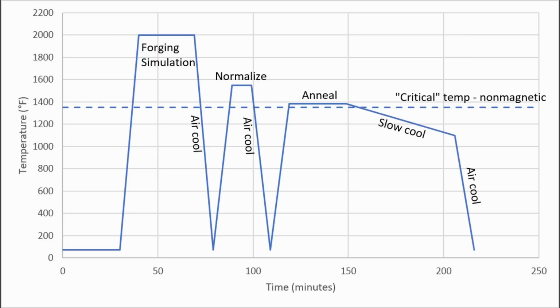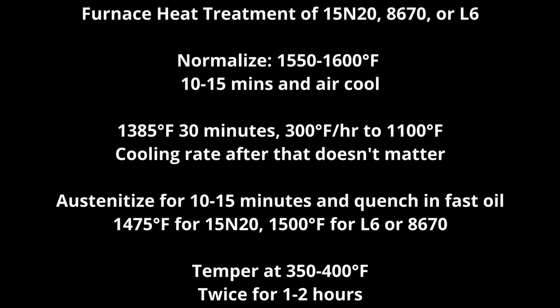It's a very low temperature process. It's just over critical. The grain is super fine, and then the slow cooling is what gives you your even carbide structure. It's all set up for the final heat treatment, and it's nice and soft for drilling and bandsaw cutting. Then you austenitize by holding for 10 minutes and quenching in oil. For L6 and 8670, because they have a chromium addition, 1500 degrees is the best temperature. For 15N20, because it doesn't have chromium, I recommend 1475.